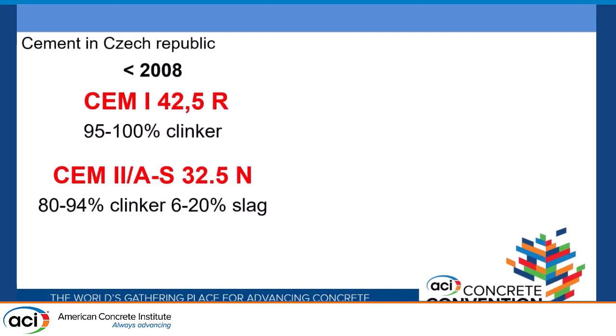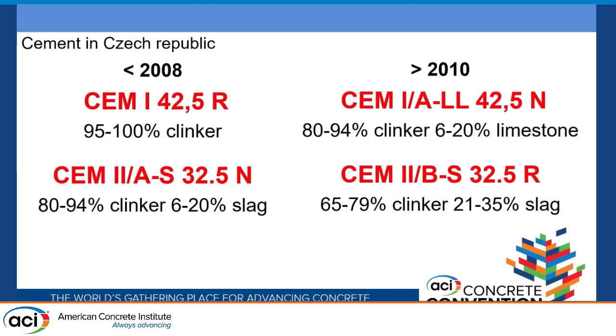So what happened after 2010? In 2010 we started to switch the country to limestone cements. And you can see how the content of the clinker changed. We went from 95 to 100% clinker to 80 to 94% for CEM 1 A, and with the other cement we went from 80 to 94% clinker to 65 to 79%. So there is a huge reduction of clinker. Yeah, so we started this transition probably in 2009. In 2013, when I left Czech Republic, all the cements and all the customers were switched to 1L cement. Yeah, so it took us 2 to 3 years to go through this.